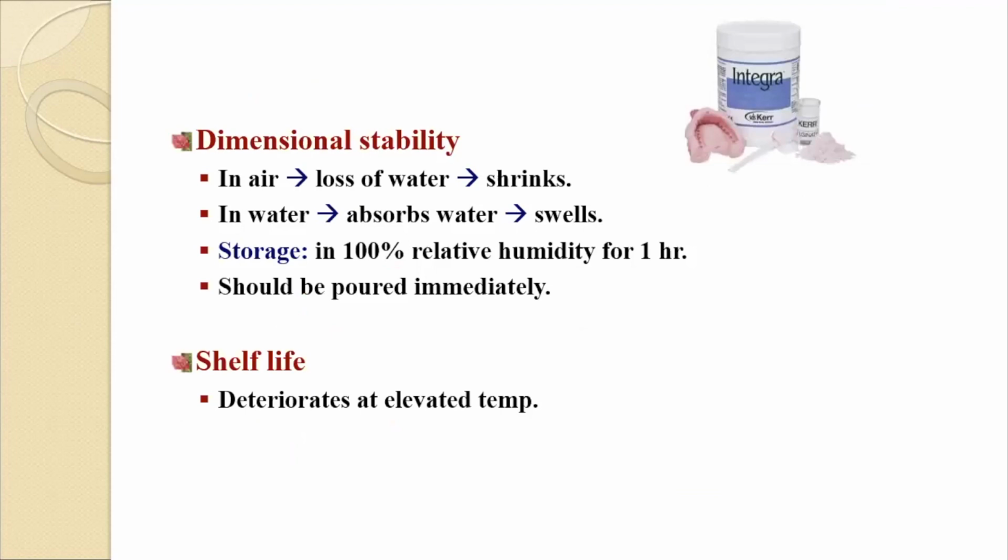The dimensional stability, in air it loses water and shrinks. In water, that is your syneresis. In water it absorbs water and swells, so imbibition. So basically it needs to be stored in 100% relative humidity, and then it can be kept for about 1 hour also, but not more than that. If so, you have to pour it immediately, otherwise. Shelf life deteriorates with elevated temperatures.